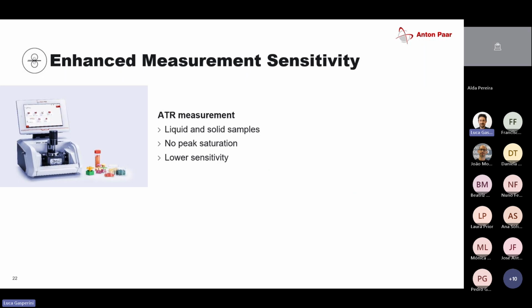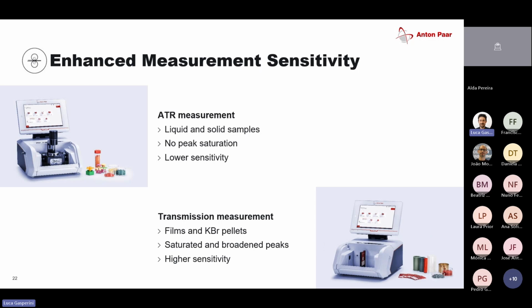Then we were also talking about ATR and transmission cell, and probably the question came up, when do I use transmission measurement, when do I use ATR measurement? So in general, if you have anything liquid or solid and there is no peak saturation, so that the sample absorbs normally as expected, and you have a little bit lower sensitivity, then you can go with ATR measurement. I would say 95% of all applications are using ATR. But then you also have the transmission measurement.